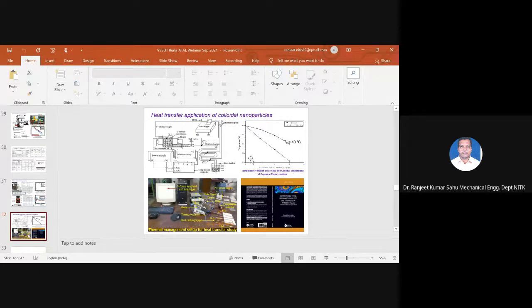Then again we took the copper particles dispersed in the PEG solution and heated it up to 40 degrees Celsius. Then we saw here that the temperature at various locations is drastically reduced as compared to the DI water. So this copper nanofluid, which is dispersed in PEG solution, can act as a high heat transfer fluid as compared to only DI water, so that it can be used in automobile applications in radiators.